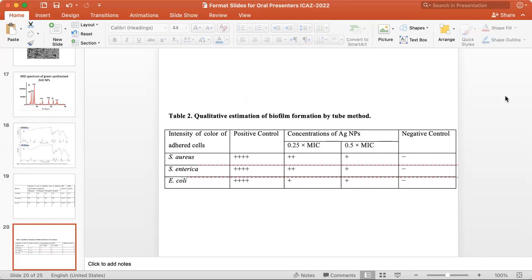Then biofilm formation. To check the inhibitory effect of nanoparticles on biofilm formation by these three pathogens, quantitative as well as qualitative methods were performed. Here are the results of qualitative estimation of biofilm formation by the tube method, and you can see here the positive control are those cells that were not treated with nanoparticles. Ring formation was there. These plus signs indicate the intensity of the color of crystal violet that was observed around the walls of the test tube.